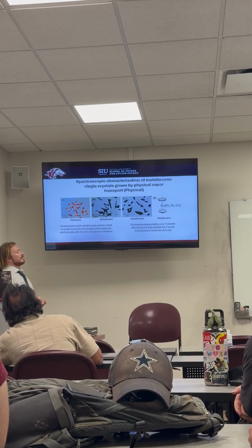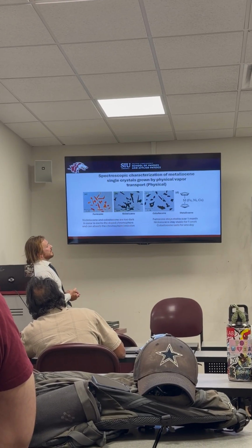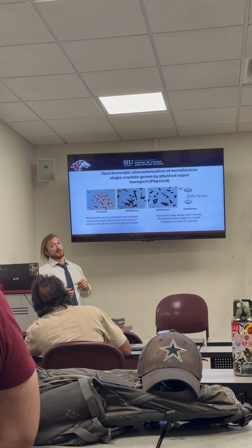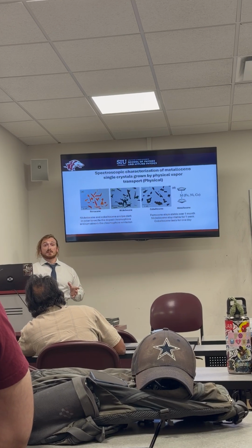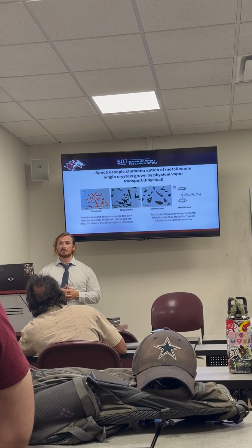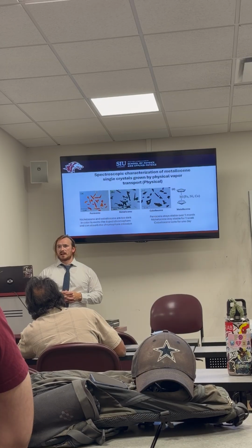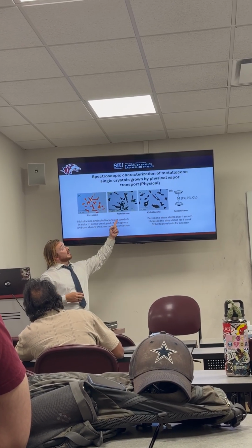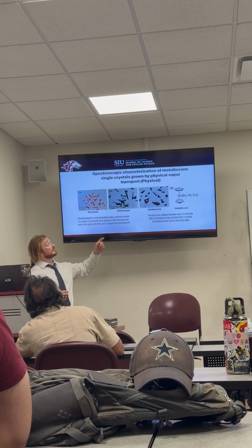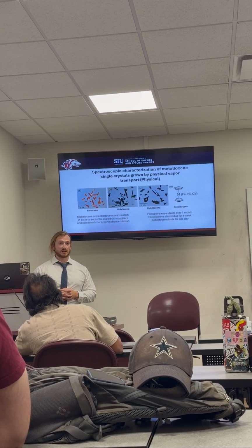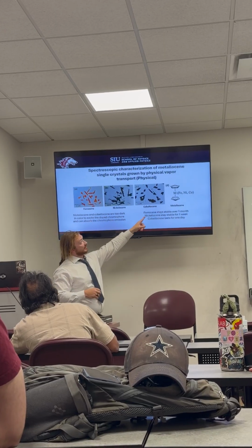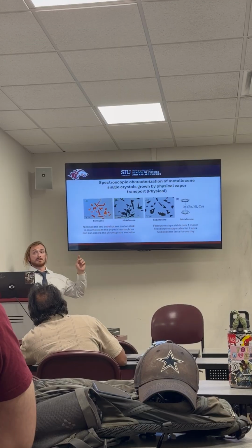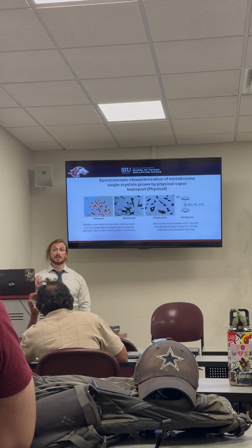Another detail is dependent on the metallocene type. Ferrocene, as documented in the literature, lasts a very long time. When I grow a sample, we can expect it to last a month, or even more, depending on the crystal thickness. Nickelocene will decay in about a week, and cobaltocene will usually decay in a day. And that's due to the metal ion size, with cobaltocene being the largest, nickelocene being the second, and ferrocene being the smallest. And that helps with the stability of that molecule.